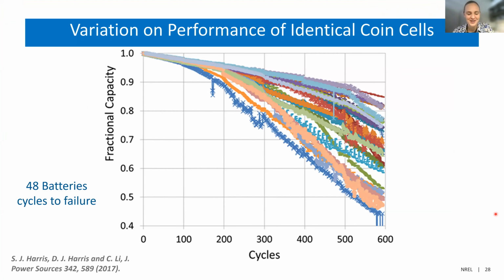What I found very interesting, and you already heard the talk from Steve Harris, is this paper that he did, which shows the amount of variation in performance with identical coin cells. We really wanted to understand why the lithium was depositing in different morphologies, but it was hard to get a good enough picture using these techniques because we had such a small sampling size. What we really needed was to see the electrodes and the whole battery stack as they exist together, so that we could understand if it's failing, why it was failing, and what was causing that.